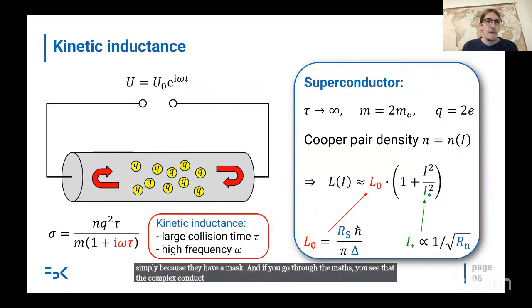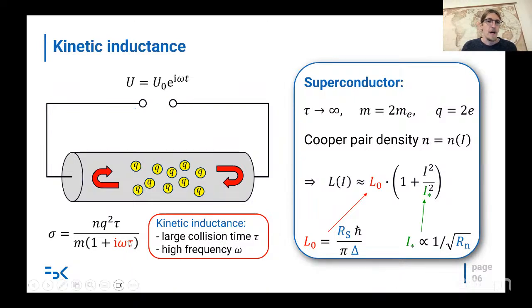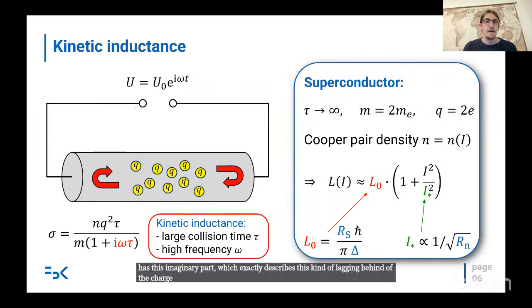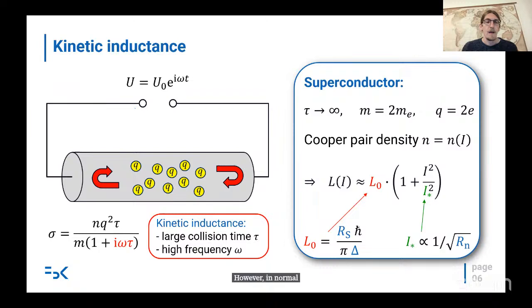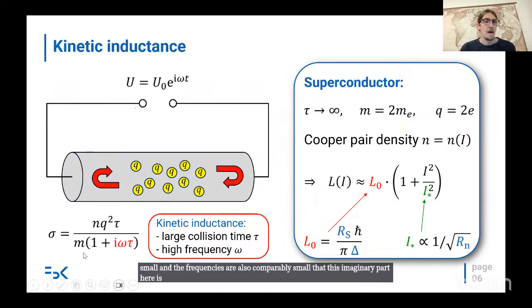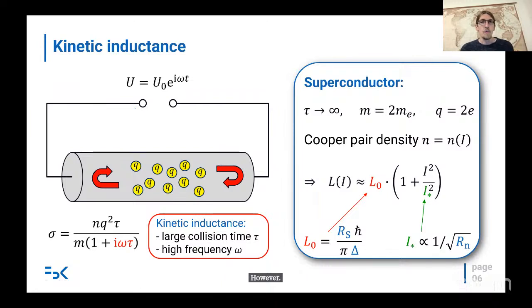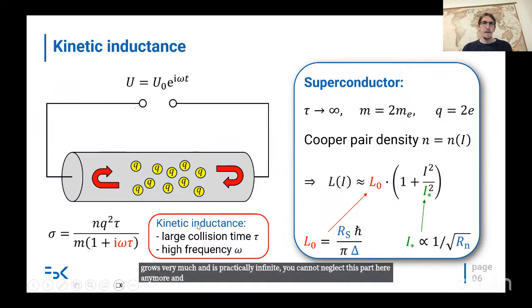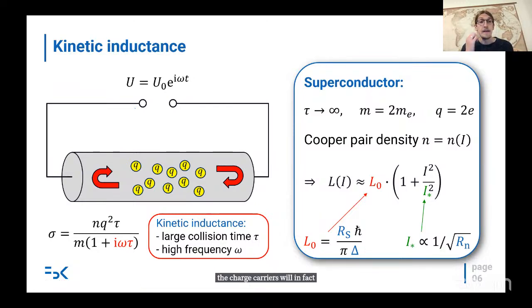And if you go through the maths, you see that the complex conductivity of each type of metal has this imaginary part, which exactly describes this kind of lagging behind of the charge carriers trying to follow the electric field. However, in normal metals, the collision time of the charge carriers, with whatever defects, is so small, and the frequencies are also comparably small, that this imaginary part here is more or less negligible. However, if you go to superconductors, where your collision time basically grows very much and is practically infinite, you cannot neglect this part here anymore, and the charge carriers will in fact lag behind the electric field that you apply to your metal.